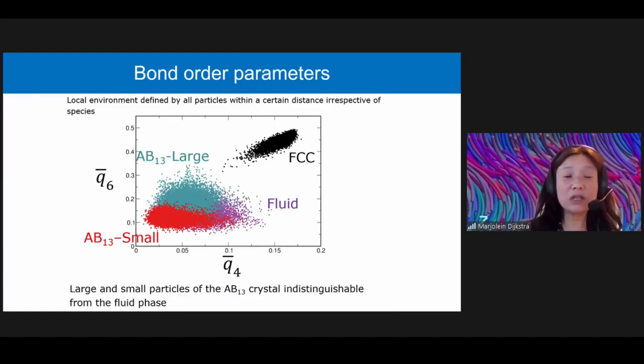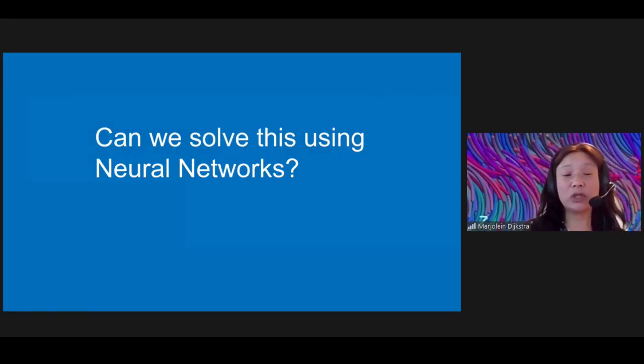And that's indeed what you also find if you use the bond order parameters. Here we use the averaged bond order parameter, and we see that all these clouds are just sitting on top of each other, which makes the identification of the AB13 phase from the fluid phase very, very difficult. And so that's why we decided to use a neural network. Can we solve this issue by using a neural network?